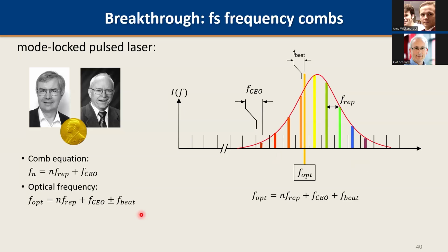Okay, I can use optical frequency combs. And then, of course, I've built a divider, because frep is typically a couple of 100 megahertz and fCEO is also at most a couple of 100 megahertz. These are very easily countable frequencies. And then through this equation, I can relate to optical frequencies by knowing the n, which I can find out actually. Then if I want to measure an optical frequency or compare optical frequencies, I make a so-called beat measurement of my laser frequency with the comb, and then I get the comb equation, that is essentially this orange line of the comb, and then I get an additional beat frequency of my laser with that particular comb line. And then I know the optical frequency.